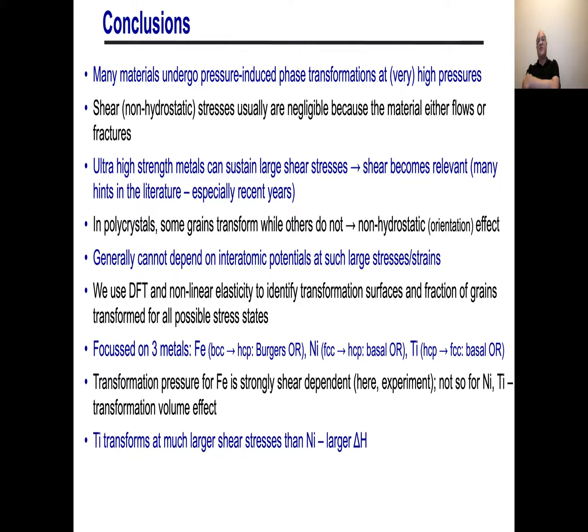And titanium versus nickel, the fact that you need much larger shear stresses for titanium than nickel is just due to the energy difference between those two phases in those two different materials. So we can understand it piece by piece.